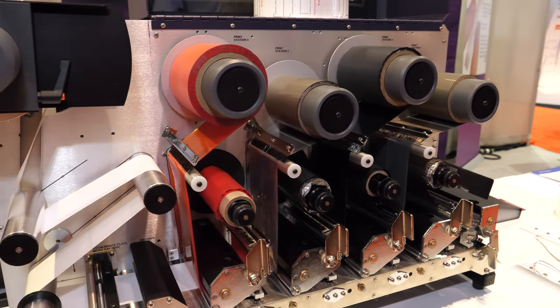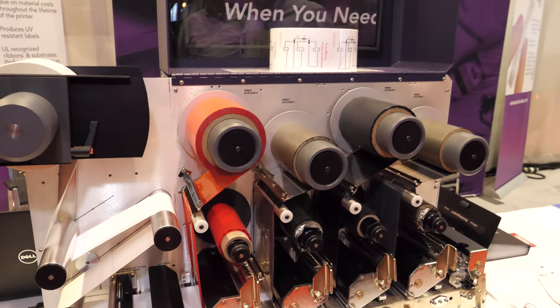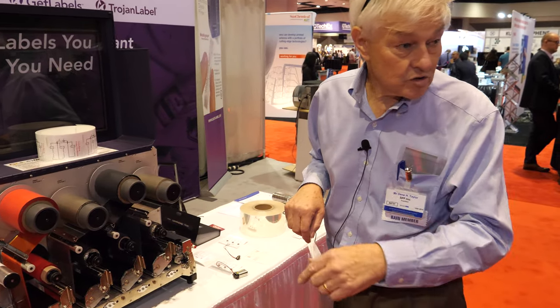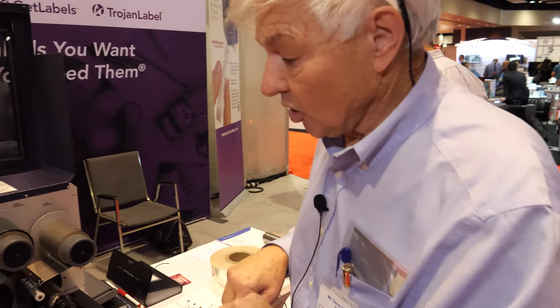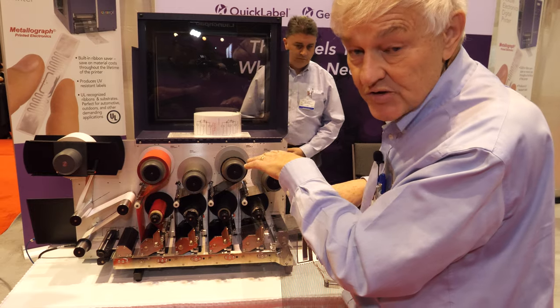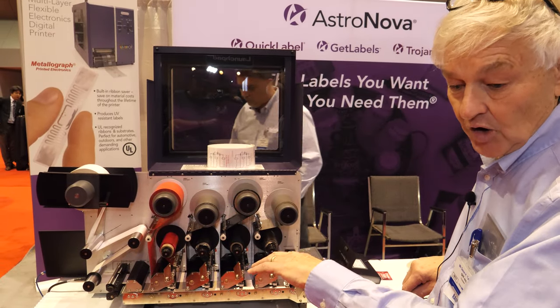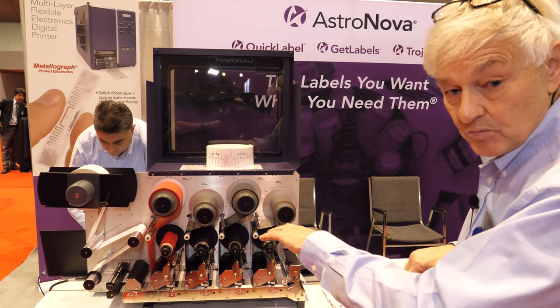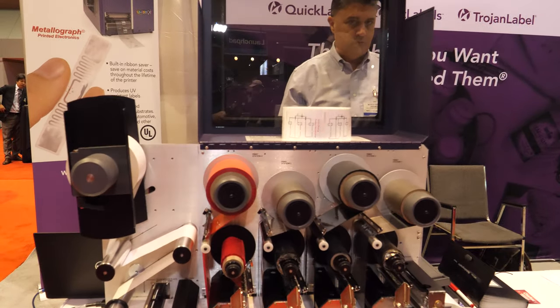We don't have the wind-up roll on it, but it runs continuously. It can print at 25 or 50 millimeters a second. The goal with this one is that we can print multiple layers — we can put down a base conductive circuit, follow that with an insulator, and then go over the insulator for conductors to have bridges.